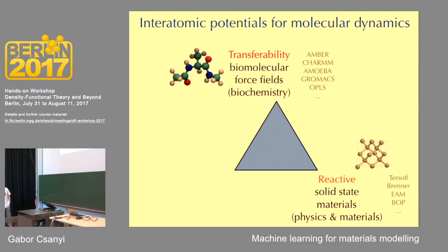And these potentials are reactive naturally. That's where the scientific questions are. But they're not very accurate, in the sense that the forces and energies you get out of them are very, very far from DFT or reality. DFT is a very good approximation of reality for these materials. But the problem is, these potentials are therefore most often not fitted to reproduce the forces. That's not how they judge, but whether they reproduce some of the science that you care about, melting points, point defect energetics, and so on. And there's a long history of doing science with them, even though they're not particularly accurate.